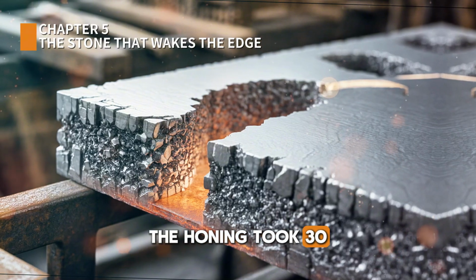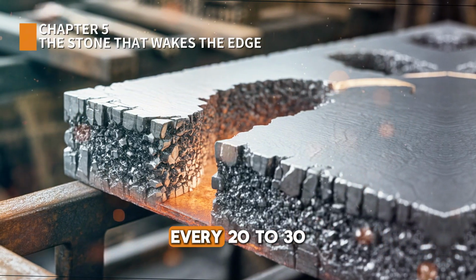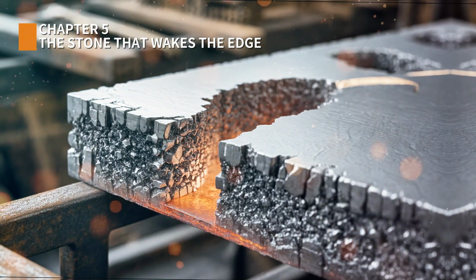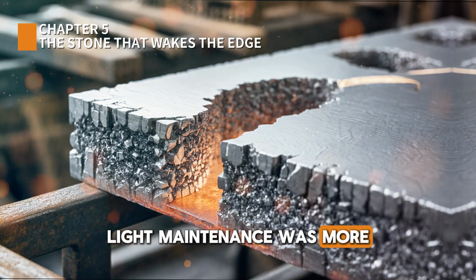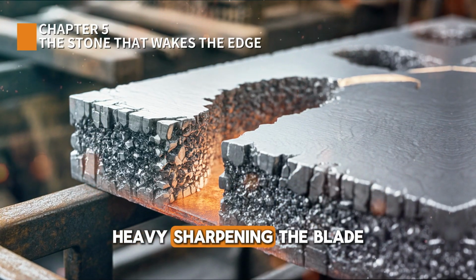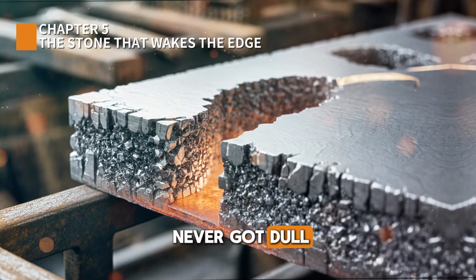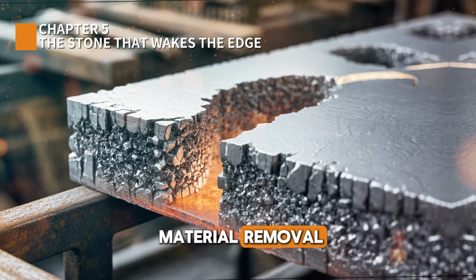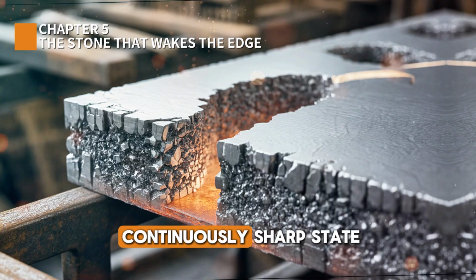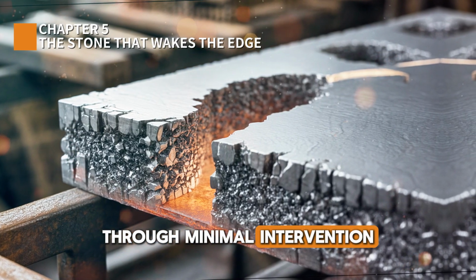The honing took 30 to 60 seconds, every 20 to 30 minutes of cutting. This frequent light maintenance was more effective than infrequent heavy sharpening. The blade never got dull enough to require significant material removal. It was maintained in a continuously sharp state through minimal intervention.